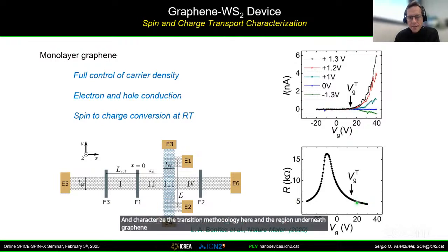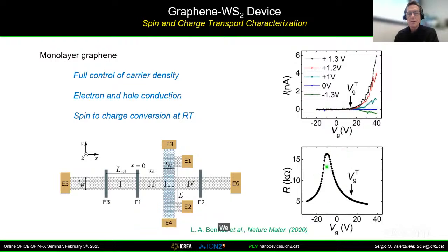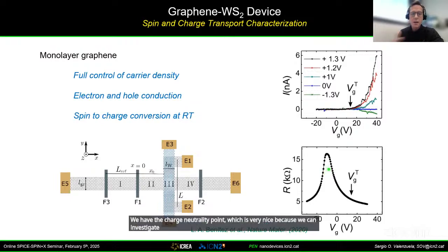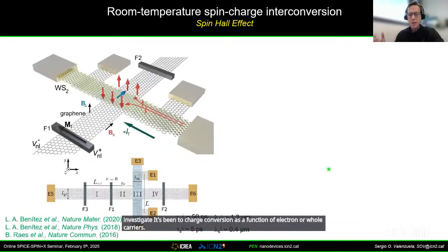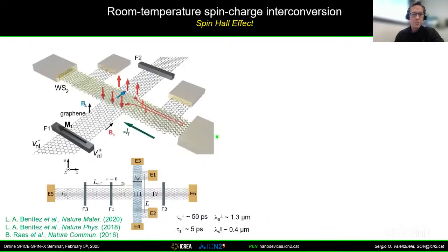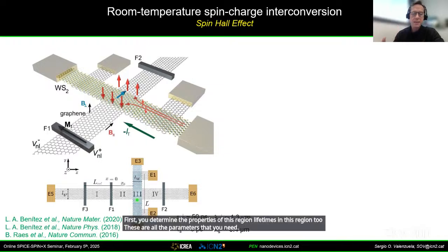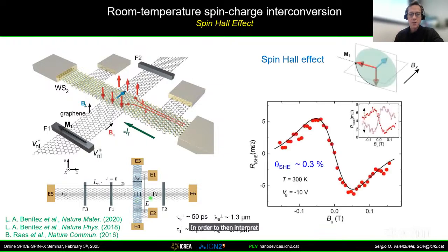And what we find is that below this threshold that I told you, we have the charge neutrality point, which is very nice because we can investigate spin to charge conversion as a function of electron or hole carriers. So first, you determine the properties of this region, spin lifetimes in this region too. These are all the parameters that you need in order to then interpret what happens with the spin Hall effect.